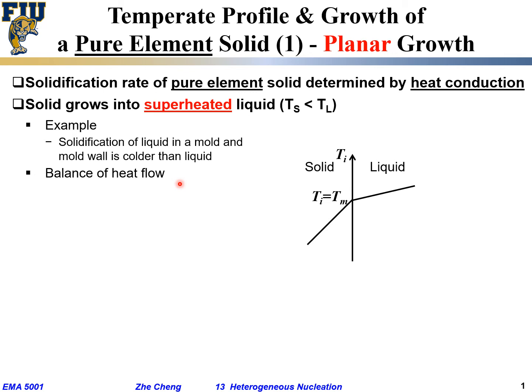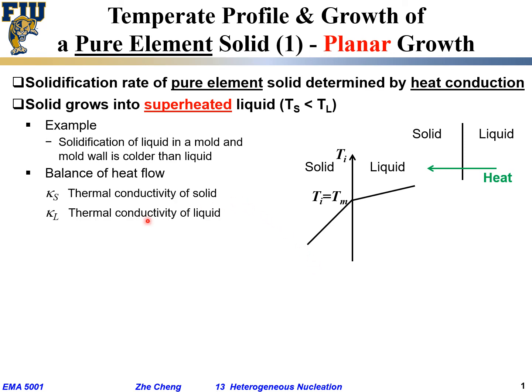And to get balanced heat flow, we have to introduce a few terms. Okay, here we plot still left side solid, right side liquid, and we said solid side is colder, so naturally the heat would flow from the higher temperature liquid side into the lower temperature, which is solid side. This is the direction of heat flow from right to left, from high temperature to low temperature, from hotter liquid into colder solid. Okay, and then we introduce a few terms. Kappa S means thermal conductivity of the solid phase, single element. Kappa L means thermal conductivity of the liquid. Of course, thermal conductivity means how fast the material, solid or liquid, can conduct heat away in this situation.